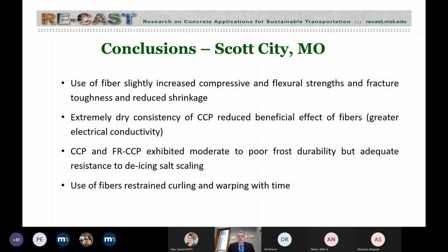that are very positive from a constructability point of view, I would say the mixture proportioning itself was too dry to start with. And then we were not able to really learn the maximum potential of the CCP technology, combined with an RCC that is properly designed and properly consolidated. So the CCP and the fiber-reinforced CCP exhibited moderate to poor frost durability, but very good resistance to de-icing salt. And then finally, the use of fibers seems to reduce the curling and warping evolution with time, which is a positive indication and probably warrants more investigation in the future.